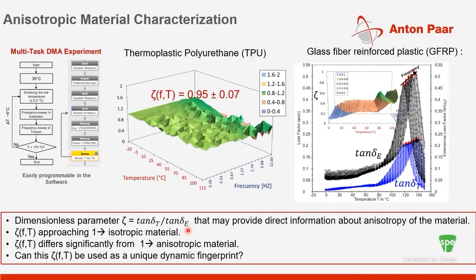The data in the center is for a thermoplastic urethane sample as a function of temperature and frequency. In this 3D plot, nothing really interesting is happening - the tan delta in both modes is sort of independent of the deformation mode, so on the whole the ratio is close to 1 within experimental uncertainties. But the second plot, the glass fiber reinforced plastic, which we know is an anisotropic material, is actually very interesting.